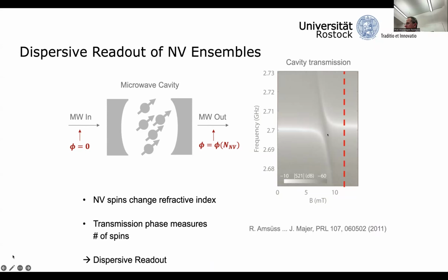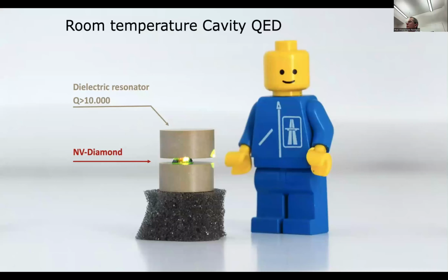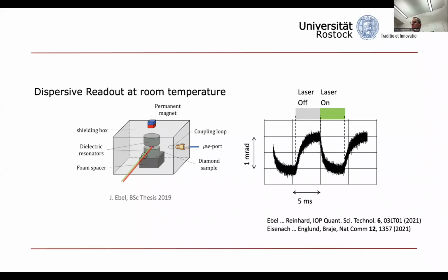At first sight, you might think that this should require a very narrow band resonator, and you might think that this would require a superconducting device, but in fact, it turns out that there are very narrow band resonators, even at room temperature, made from low loss perovskite ceramics, which can achieve quality factors like superconducting stripline devices in a room temperature device. So this is one of them. This is an NV diamond sitting in between. And this is something that we recently used in an experiment to read out the state of the NV centers.